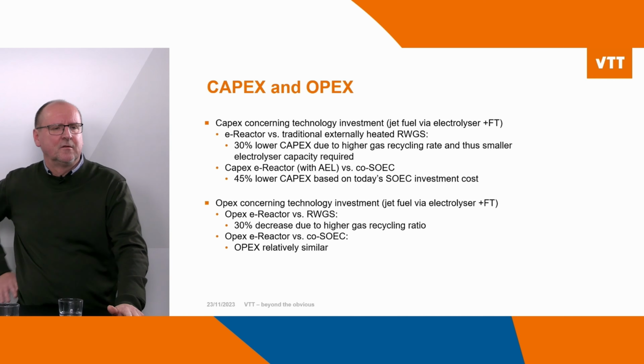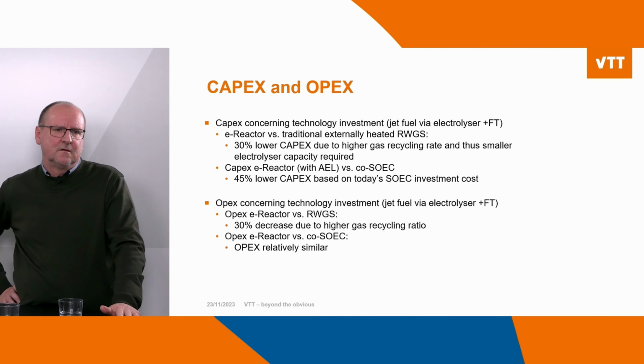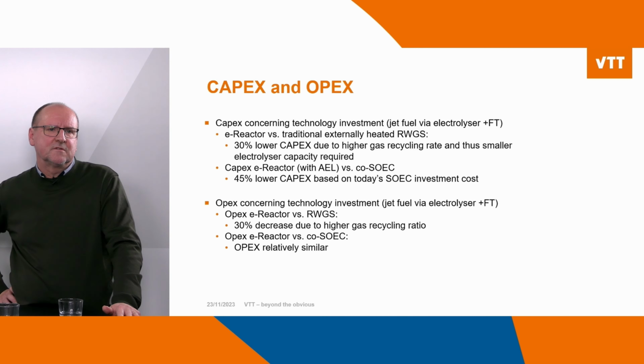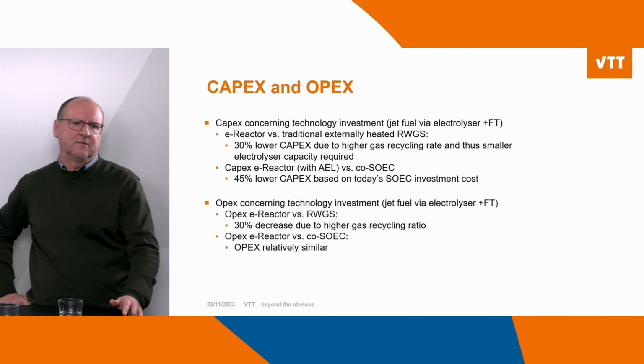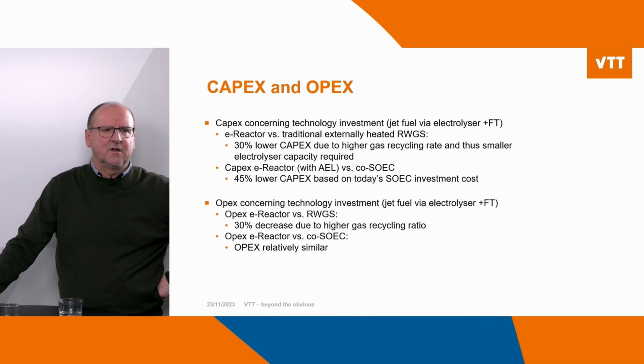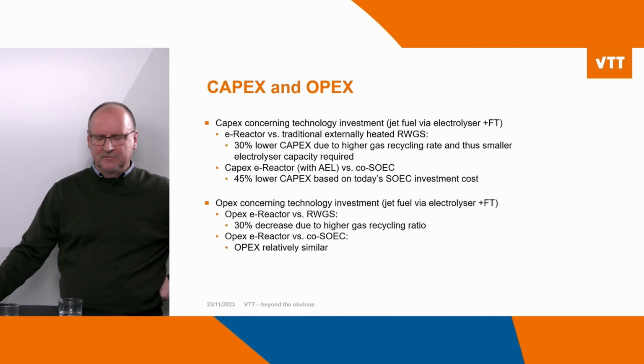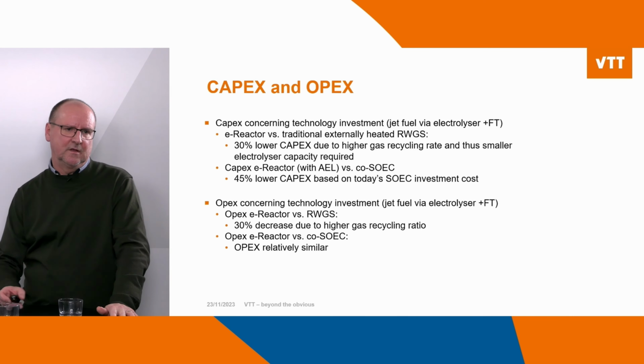And then about operating expenses concerning technology investment, so jet fuel, for example, produced by this electrolyzer plus Fischer-Tropsch reactions. So OPEX of this E-reactor is about 30% smaller due to higher gas recycling rate. And OPEX of E-reactor versus SOEC, they are at a similar level, so no big differences in that.